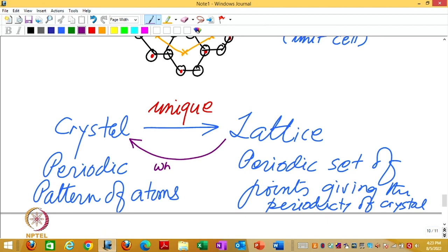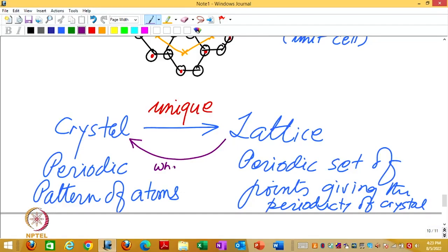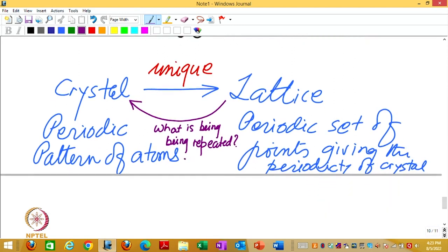It is telling you something is being repeated, the pattern has this periodicity, but it is not telling you what the pattern consists of. So, you need what is being repeated as additional information. And this what is being repeated is given a name, and that is called a motif.